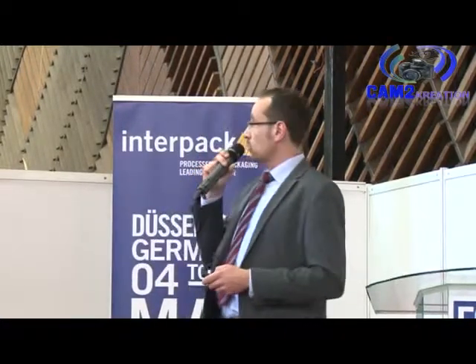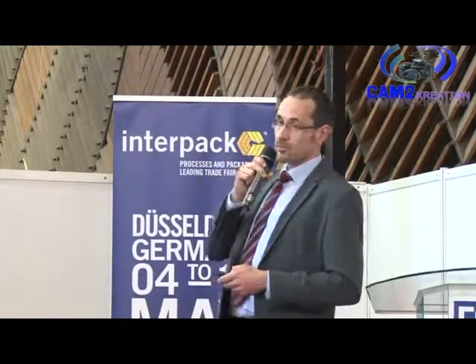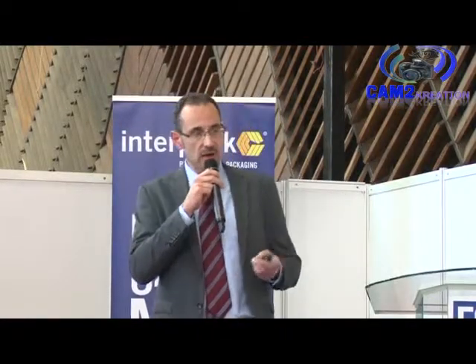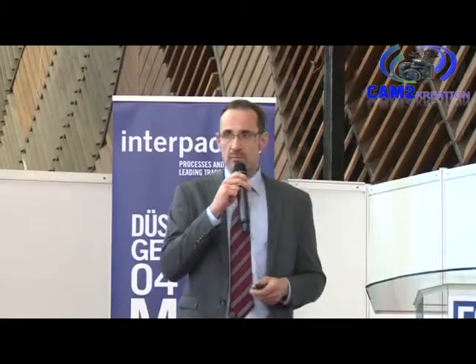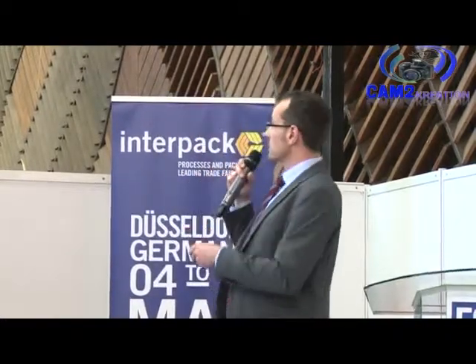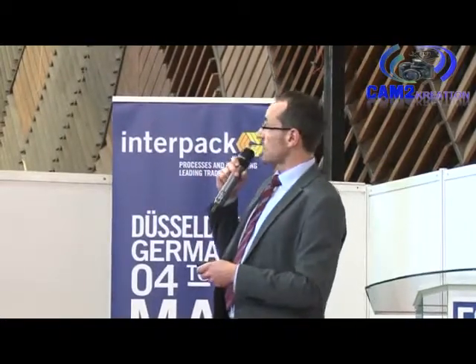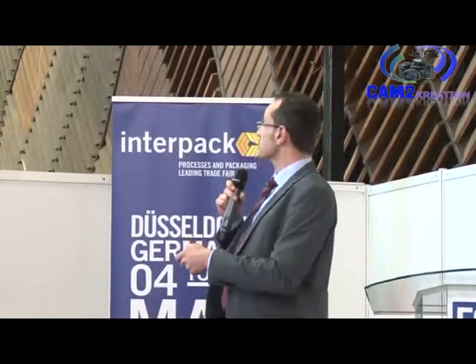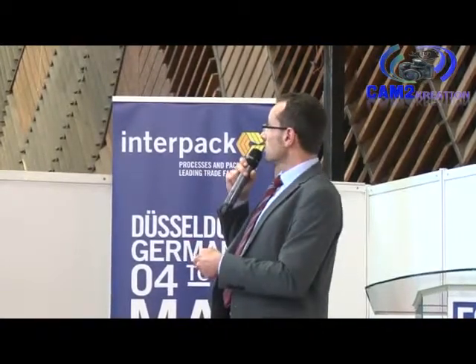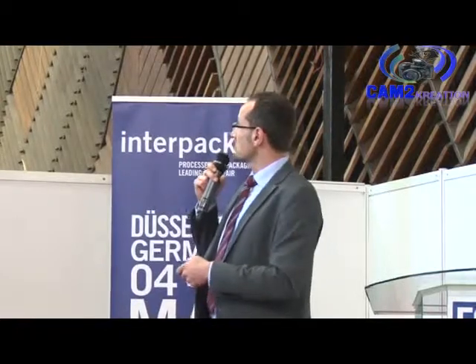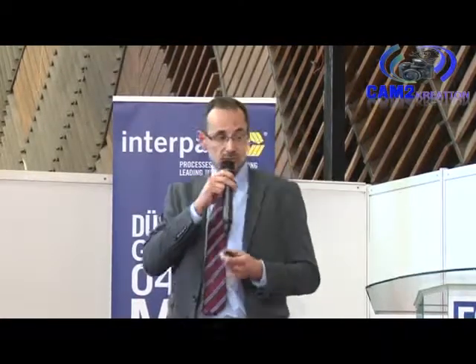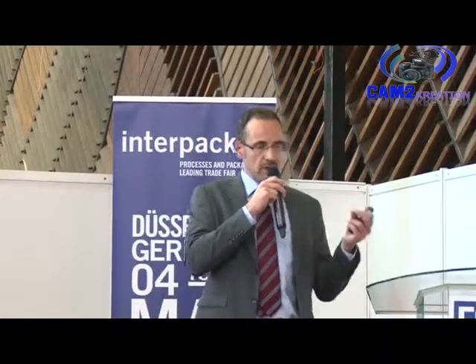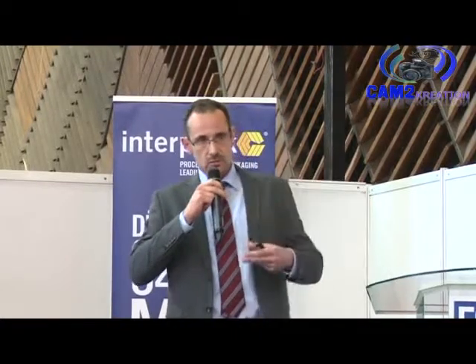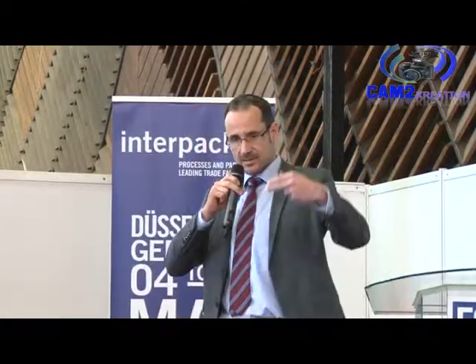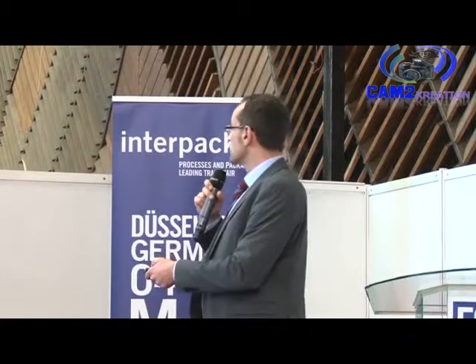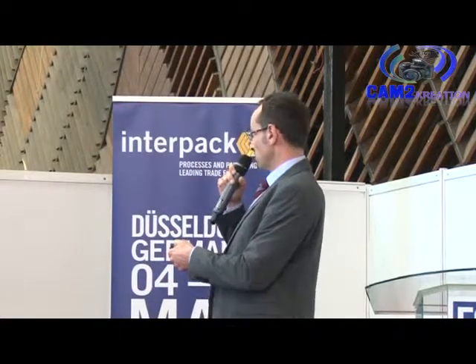So now the next point is how polyamide is converted into films, because here I think the main applications will be films. We have three fundamental processes. One is the so-called cast film process. In that case, the melt will be brought by a flat die onto a chill roll. So it's a flat die where the melt is coming out, as you can see here.